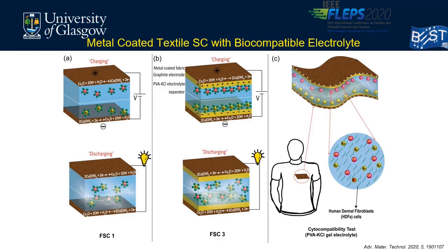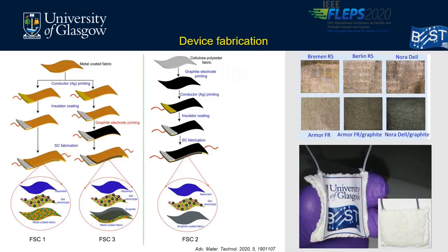Here we have fabricated a supercapacitor based on metal coated fabric as the electrode. Then we enhance the capacitor performance by including a graphite electrode on top of this metal coated fabric. Then finally we have investigated experimentally the biocompatibility of the formulated gel electrolyte through cytocompatibility test with the human dermal fibroblast cells. For that study, we have fabricated the devices.